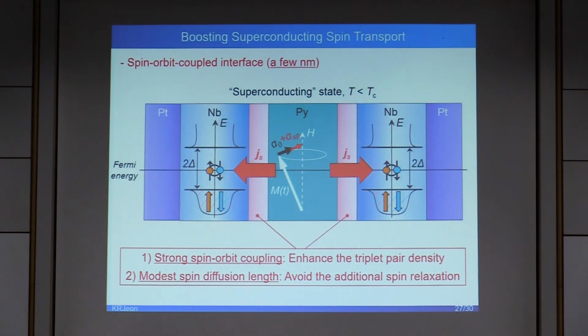Last but not least, let me briefly introduce our latest work, namely that a further improvement of superconducting spin current can be achievable by introducing a spin-orbit coupled interface in between the ferromagnet and superconductor. The idea is to enhance the total spin-orbit coupling induced triplet pair density without modifying the spin propagation between the ferromagnet and the superconductor, by inserting a few nanometer thick interfacial layer which has strong spin-orbit coupling and modest spin diffusion length.